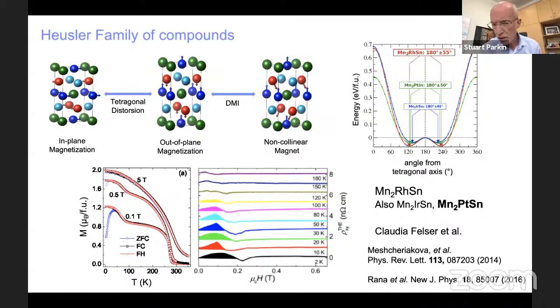where they make these fantastic single crystals of a wide range of materials. And the materials of interest are Mn2 rhodium, iridium, or platinum tin compounds as shown here. And the concept is, if you look at the middle tetragonally distorted structure, you can see there are layers of these manganese atoms. They're shown as blue and red atoms, and they have different environments, and so the moments are different. And interestingly, in these structures, the manganese moments on the blue and red respective sites are coupled antiferromagnetically, leading to a net